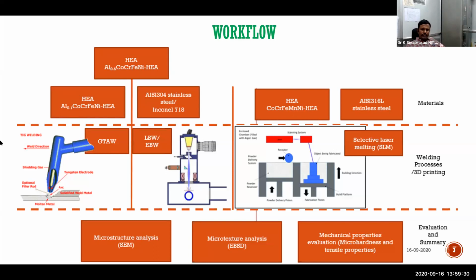We made sure that if this is a single phase FCC, this is also a single phase FCC. This is giving a particular strength and ductility combination. This is also giving almost similar strength and ductility combination. So we have chosen the system in such a way that it is comparable. Then here also austenitic stainless steel, again 316L and 304. We have taken again similar strength and ductility combinations, comparable work hardening behavior especially, and comparable weldability.